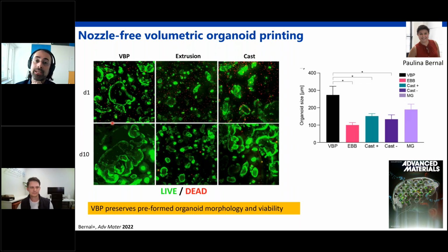But the way we do it here is in a spinner flask bioreactor. So we don't culture them in gel. We take the single cells, we add them into media, and we pour them in a spinner flask. And there is a little bit of Matrigel in the suspension, because these cells do need laminin and collagen 4 to grow. Potentially, you could replace that Matrigel with recombinant proteins, but there are still some compounds in Matrigel that we don't know exactly what they do, but we need them. So they grow in the spinner flask and they form organoids in suspension. So they're not attached to the Matrigel itself, but we do need a bit of Matrigel in the media.